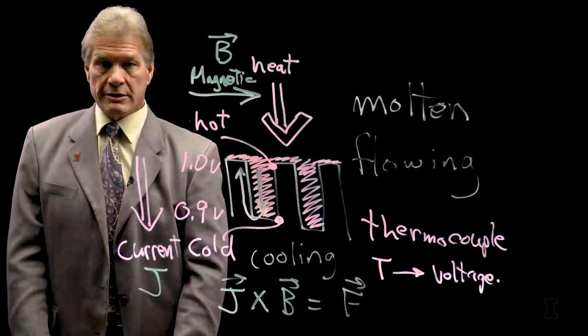And it actually works. Here you see a video that shows time-lapse photography of the molten lithium in the trenches. Notice they're slightly underfilled. And as the electron beam, the heat source, goes on, you can see that the velocity increases as it goes across. So this sounds really cool, and you saw that we can actually do it in our lab. And then the question is, well, does it work anywhere else? Can you put it in a real fusion device?